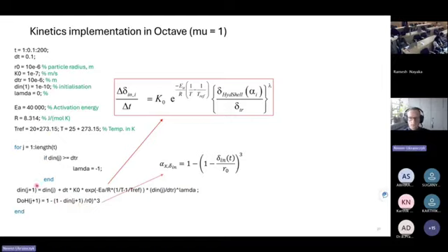And here I just added this threshold thickness. If that penetration depth is bigger than the threshold, then you switch the lambda, which is initialized as 0, to -1. When it's 0, you don't have any influence, the factor is 1, so there is no effect. But when you enter the diffusion mode and reach some threshold thickness, you basically switch this to -1.